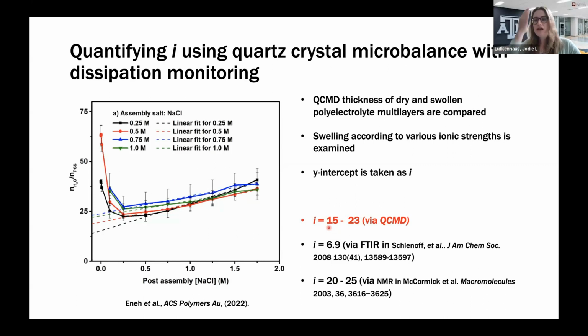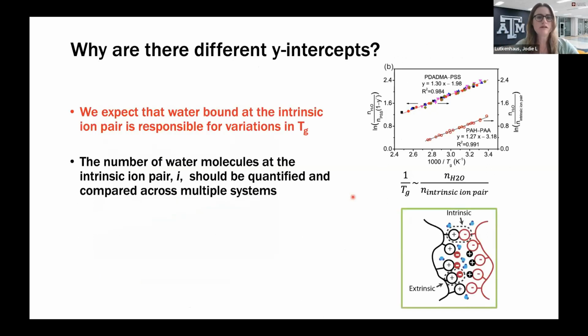And what we find is that we're getting 15 to 23 water molecules per intrinsic ion pair, which sounds really high. I mean, if you think about an intrinsic ion pair and then something like 20 water molecules around it, it sounds a little crazy, but at the same time, other methods like NMR have seen 20 to 25. The FTIR method I mentioned showed 7 or 6.9 water molecules here. So what we think is, depending on the method you use, you're probably accessing water in the first hydration shell, and maybe with our methods, outer hydration shells that are correlated with the intrinsic ion pair, but less so than that first hydration shell. So that is one of these methods that we're considering to address the y-intercept. But if you stay tuned, I'll give you another thing to think about for that y-intercept.